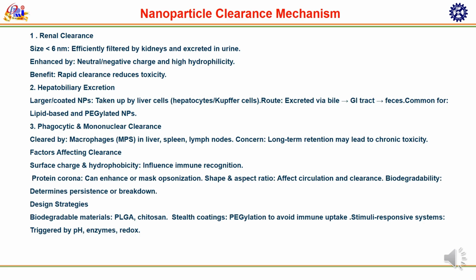Factors affecting clearance: surface charge and hydrophobicity influence immune recognition. Protein corona can enhance or mask opsonization. Shape and aspect ratio also affect circulation and clearance. Biodegradability determines persistence or breakdown. Design strategy: biodegradable materials like PLGA, chitosan, Stealth coatings: PEGylation to avoid immune uptake, and stimulus-responsive systems triggered by pH, enzyme, and redox.